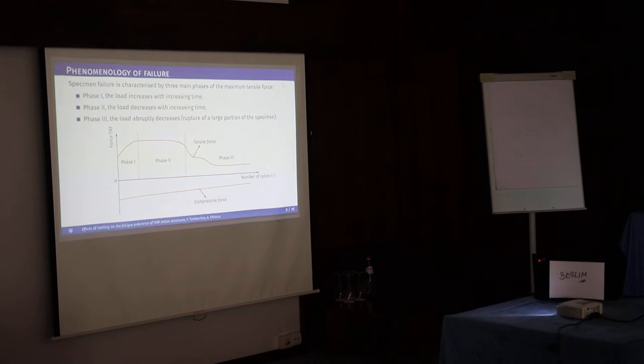This is the qualitative behavior of the force during the loading cycles versus the number of cycles. We can identify three main phases. I wanted to stress that the range, the number of cycles of each phase, is not realistic here - phase one is quite short compared to the other phases. We have a first phase where the load increases slightly while the time increases. Then we have almost like a plateau, and then the load starts decreasing until an abrupt rupture of the specimen. A lot of struts break down, and we have a kind of staircase behavior, so the specimen is going to break completely.